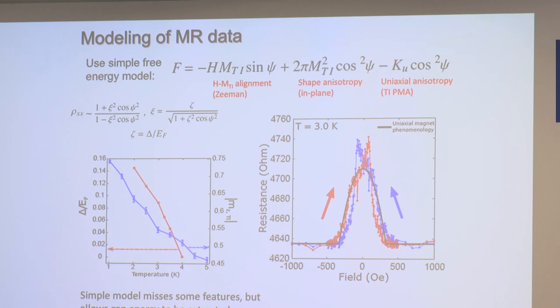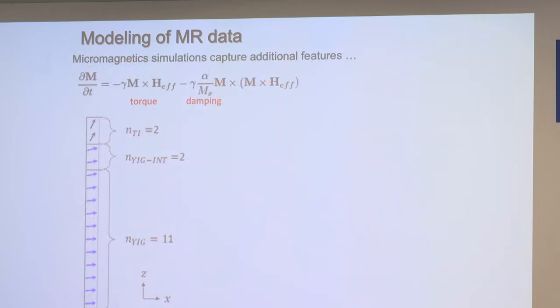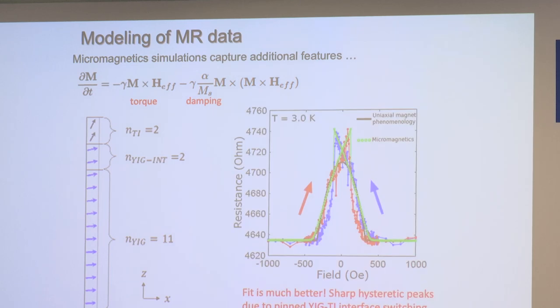So if we then model it using micromagnetic simulations, with a layer of a topological material, an interface with YIG, and then YIG on the bottom, we can exactly model this. This is simply micromagnetics, looking at a layered material and at what happens if you have the magnetization at the interface rotating with the field. And you can see that we fit that really well. These peaks here seem to be due to the pinned YIG-TI switching. And as was mentioned, this happens at fields 50 times larger than what would happen with YIG alone. So there's some interaction that's actually changing the anisotropy in the YIG with the coupling to the bismuth selenide.